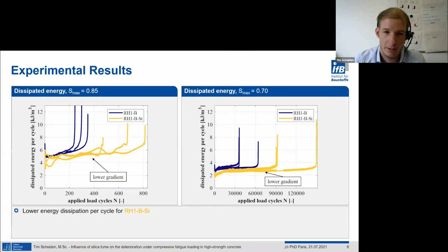The next strain-dependent damage indicator is the dissipated energy as a measure for the viscous behavior, calculated as the area of the hysteresis loop in the stress-strain development for each load cycle. At the higher stress level on the left side, a lower initial dissipated energy and a lower energy dissipation per load cycle in phase 2, here in the middle, for the concrete with silica fume is recognizable.